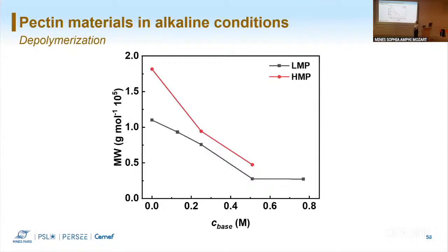Yeah. In the literature, there was one work where they noticed this phase separation. Their theory was that there is a salting of the ionic carboxyl group, and then the chains interact, and I'm not sure what this publication wanted to say, but, sorry. Yeah, it's not easy. The system is very special, and as you say, at high pH it's a bit tricky.